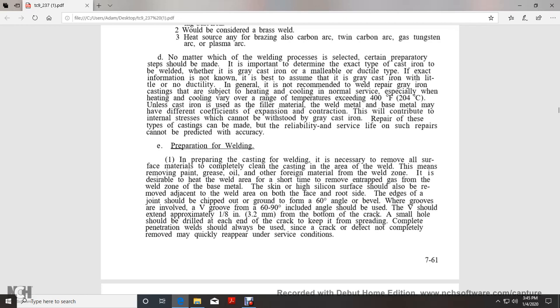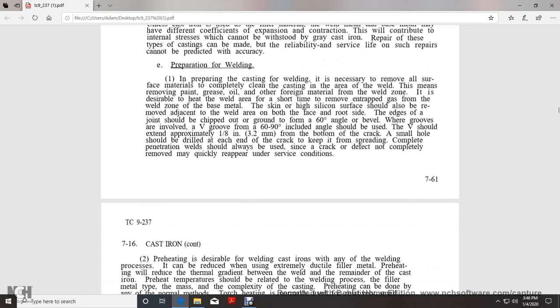The best assumption is gray cast iron, which has little or no ductility in general and is not recommended for welding. Repair-welded gray cast iron is subject to heating and cooling in normal service, especially where the heating and cooling vary over ranges exceeding 400 degrees Fahrenheit. Unless the filler metal is cast iron, the weld metal and the base metal may have different coefficients of expansion and contraction, which will contribute to internal stress that cannot be withstood by gray cast iron. Repair of this type of casting cannot be welded with reliability, and the service life of such repairs cannot be predicted with accuracy.